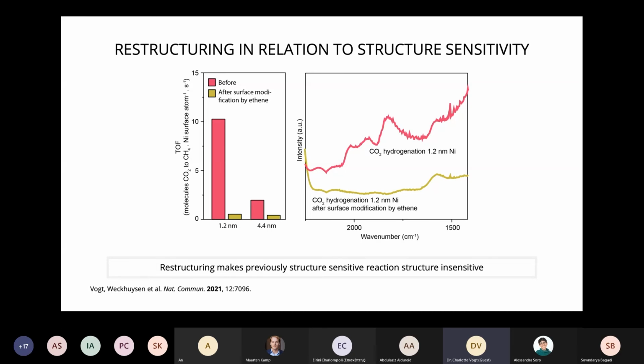This is a hypothesis that was already proposed by Somorjai somewhere in the 80s, along with a couple of other hypotheses, because he also thought that it's quite strange that surface structure insensitivity exists. If it is the case that something adsorbs irreversibly onto the surface, and irrespective of the previously exposed surface, only exposes a certain amount of, or certain type of, sites, then yeah, irrespective of the nanoparticle size, there will always be the same, or nominally the same, surface sites.